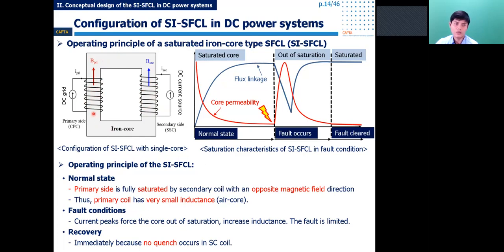And when the fault occurs, the current increases very fast, and the core is out of saturation. So the inductance increases and limits the fault. After fault clearing, the SI-SFCL can immediately recover because there is no quenching on the superconducting coil.